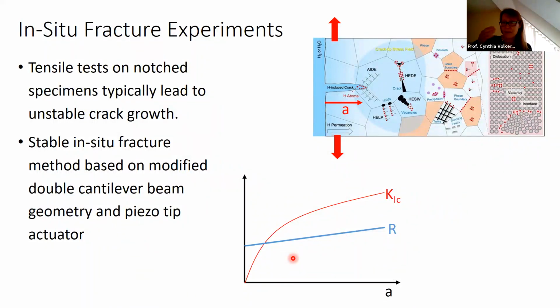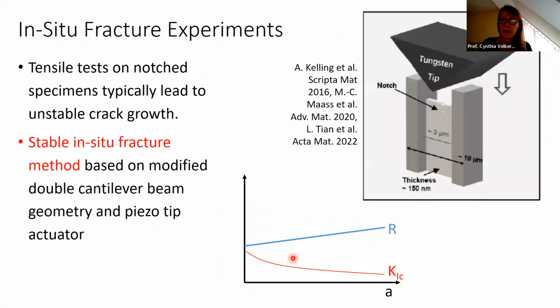So that's the problem with putting a specimen into the TEM and just pulling on it and trying to look at the crack tip. It will inevitably become unstable and move much too fast to investigate it. So we made a different design, which is a modification of the so-called double cantilever beam geometry. And you can see the geometry here. We cut out 2 posts of material with a thin lamella in between.